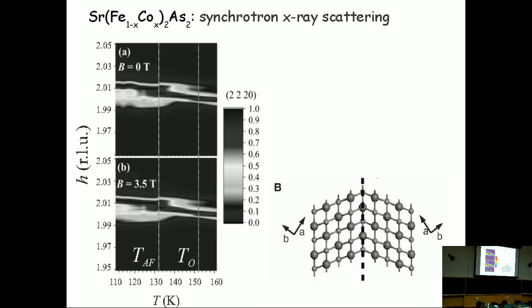And we also studied, again, as I said, the 122 system, okay? And this sample we have to characterize better because it was not previously studied. So we did synchrotron X-ray diffraction. Here, I'm not going to get into too many details, but at high temperatures, we have this 220 reflection, which is supposed to be a single reflection. So that's what we see at high temperatures.